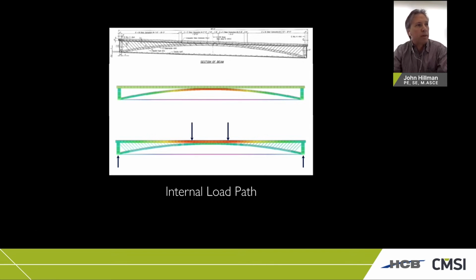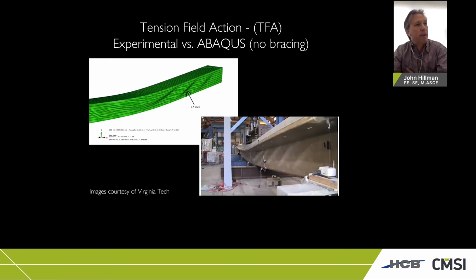If we put a quarter point load test on here, what we see is that we get the compression going down the arch, steel tension tie along the bottom, and then the shear is actually carried in tension field action along the webs of the FRP until we get to the ends of the beams where it begins to be carried by the concrete arch and fin. So it's really quite a fascinating load mechanism. This gives you a good example of comparing an experimental load test to a finite element analysis using Abaqus with some very high level contact surfaces and nonlinear elements. And you do actually see the tension diagonals for the shear develop from the load point out as opposed from the bearing in, which is sort of counterintuitive to what we do with steel, but again, it's basically because of the load sharing mechanism between the FRP webs and the reinforced concrete.